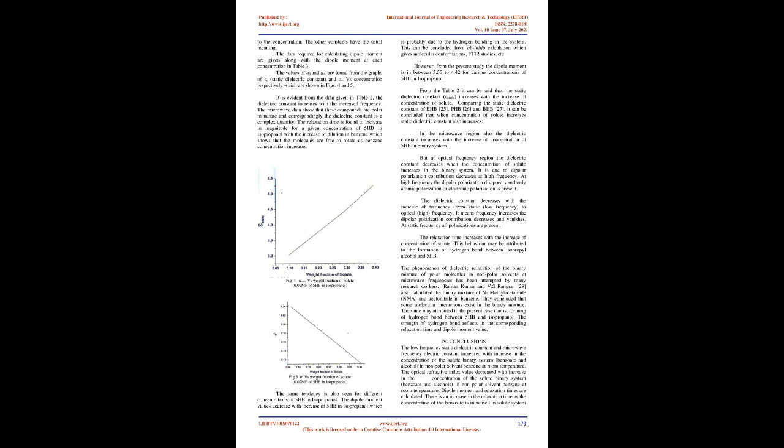It is observed that a distribution of relaxation times is witnessed from the Cole-Cole arc plot instead of a Debye arc plot, which signifies the distribution of relaxation times. Eventually a macroscopic relaxation time, the predominant relaxation time, is computed using Cole-Cole plots.